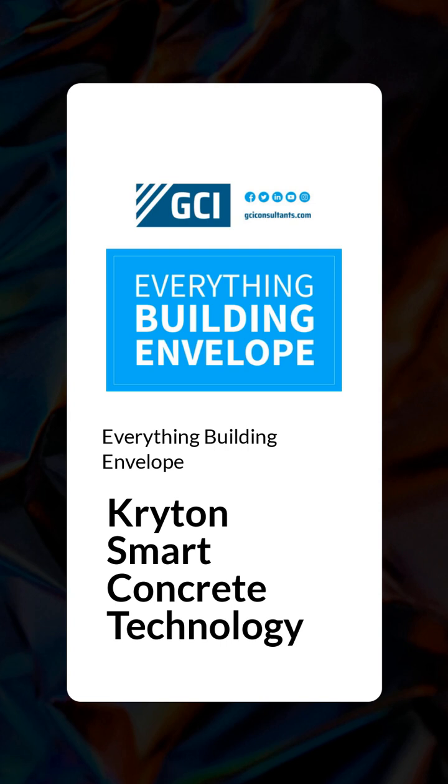Sure. Well, Kryton technology, it's a trademark term simply to describe the crystalline technology, and it goes in with the products that we have. So it's added directly to the concrete mix or applied to the surface of concrete. And once added, the Kryton chemically reacts with water and unhydrated cement particles to form insoluble needle-shaped crystals. And these crystals fill capillary pores and micro cracks in the concrete to block pathways for water and waterborne contaminants. As well, the crystal will continue to give the concrete structure a self-sealing ability. So if water is reintroduced through a rise in hydrostatic pressure or through hairline cracks or through voids in concrete, the crystals will initiate further crystallization to ensure essentially permanent waterproof protection. And this happens for the life of the concrete.